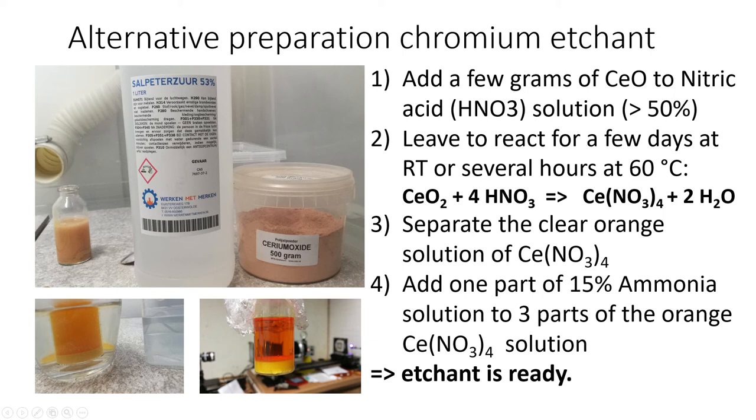Now, the cerium oxide does not immediately react with the nitric acid. However, if you heat the solution to 60 or 80 degrees Celsius, it will react to cerium nitrate in a few hours. You can see this because the solution will turn brightly orange.